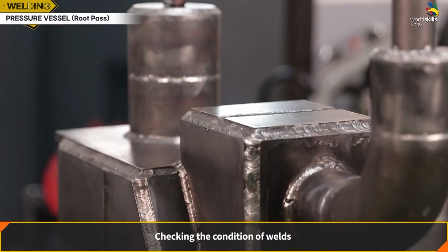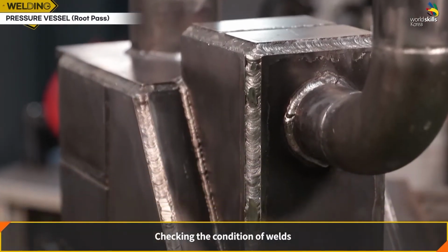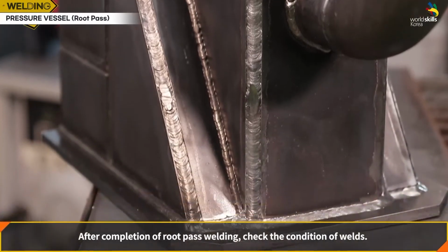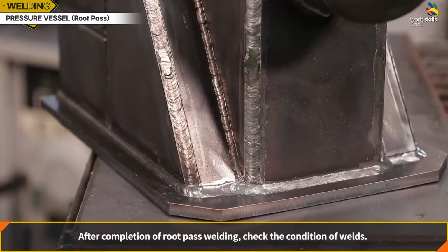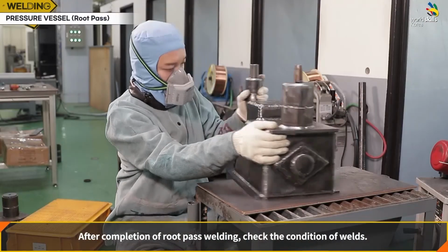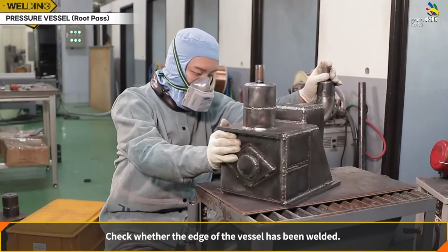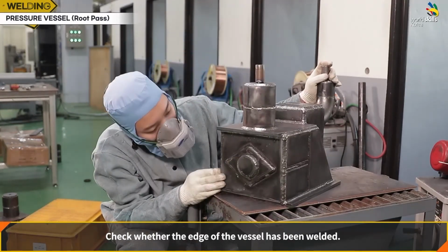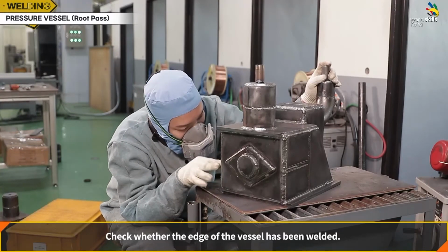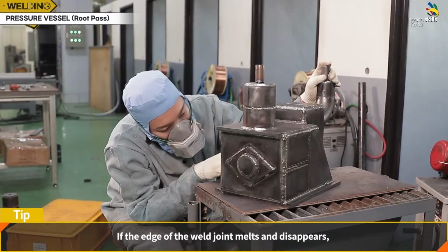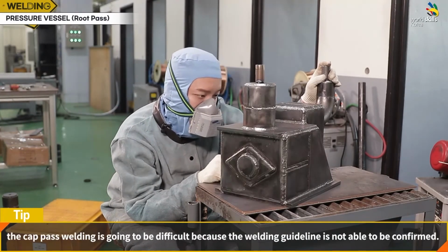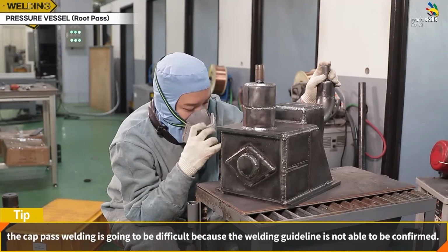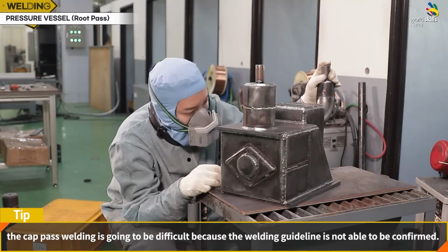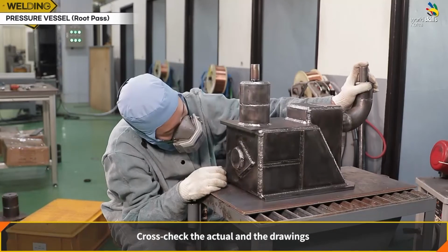Checking the condition of welds. After completion of root pass welding, check the condition of welds. Check whether the edge of the vessel has been welded. If the edge of the weld joint melts and disappears, the cap pass welding is going to be difficult because the welding guideline is not able to be confirmed.